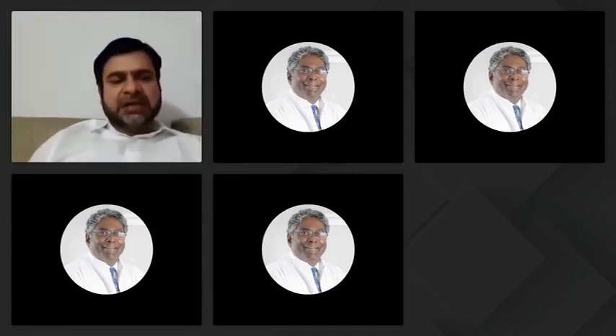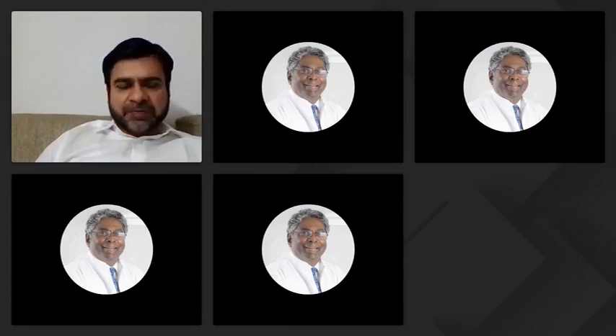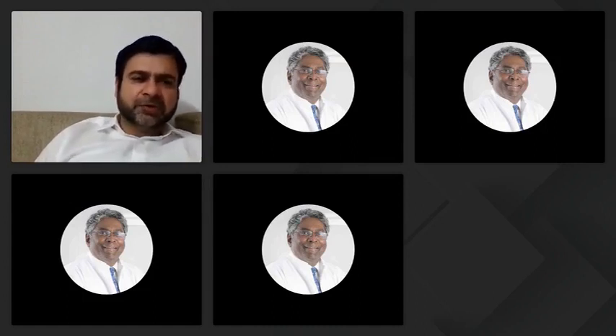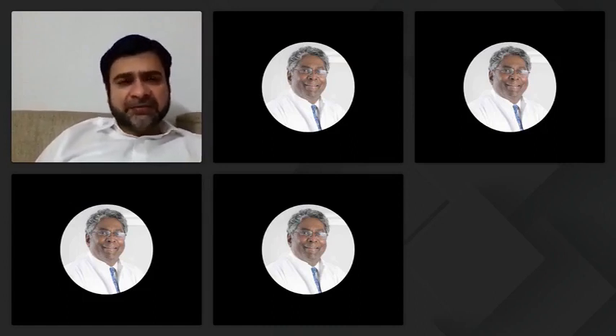In our system, of course, I could not show that slide because of the paucity of time. We had calculated the bone loss pattern around our implant as well as the controls. So it was very much within the range of about a millimeter or millimeter and a half post loading. And in some cases, what we found was there was hardly even 0.5 millimeter of bone loss, especially the case that I showed you of 7 years of follow up. So there, the crestal bone was quite preserved.